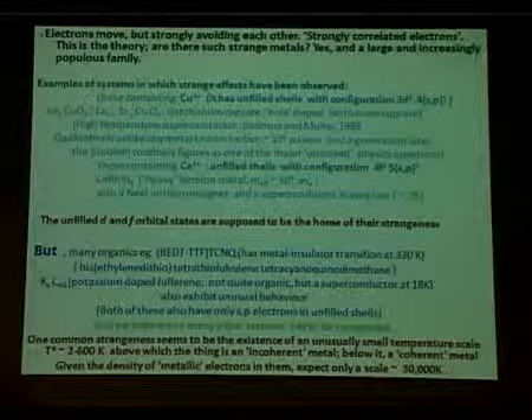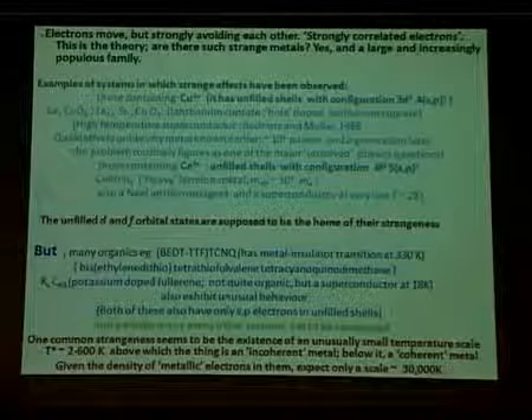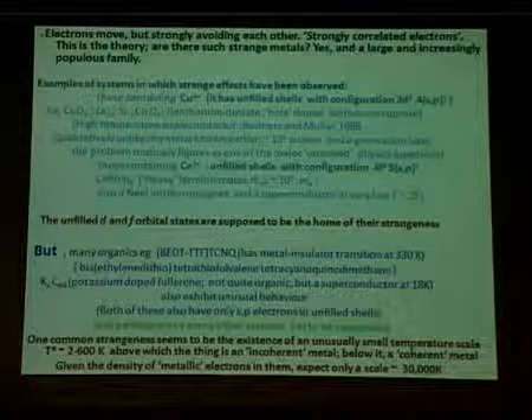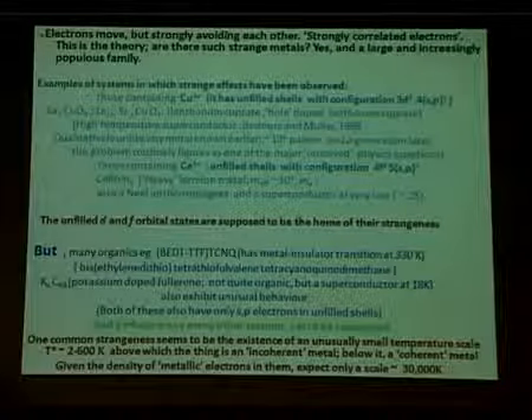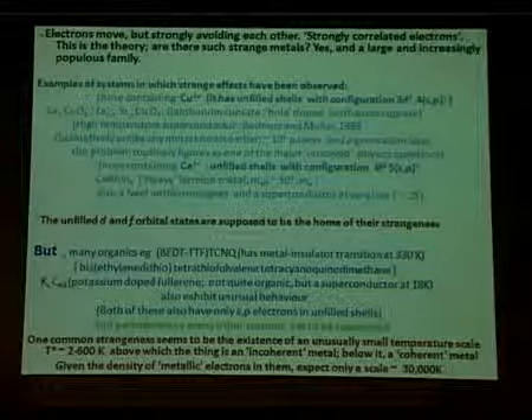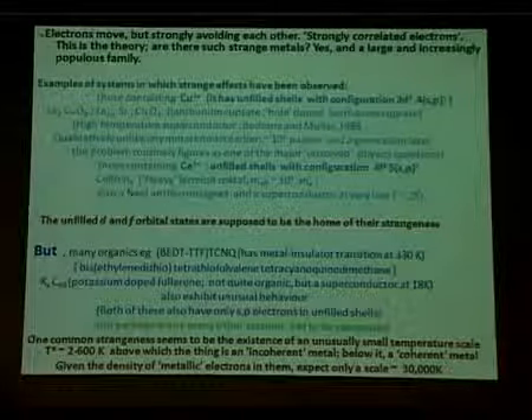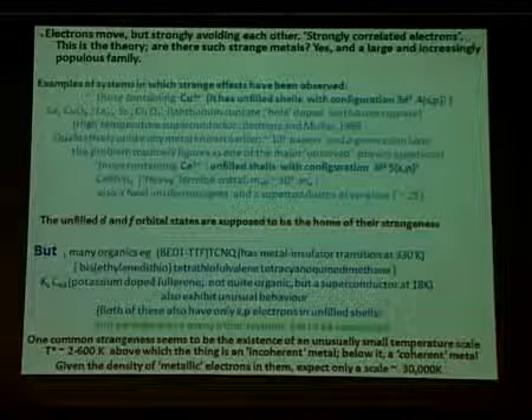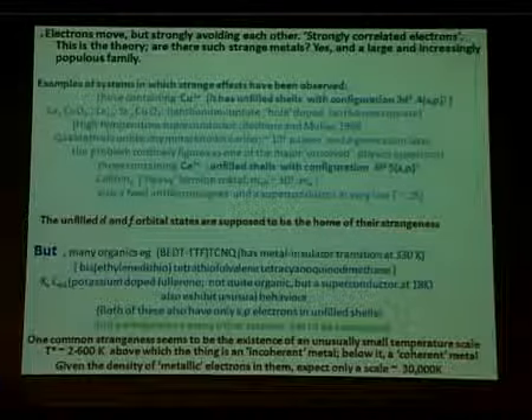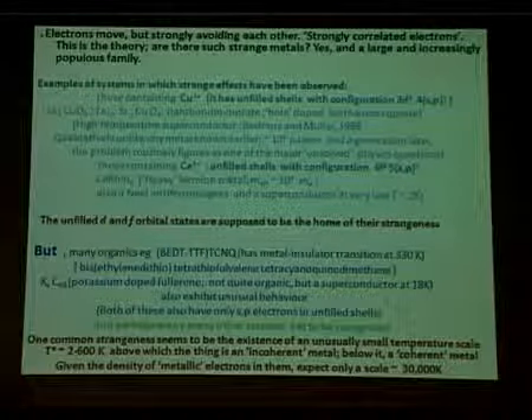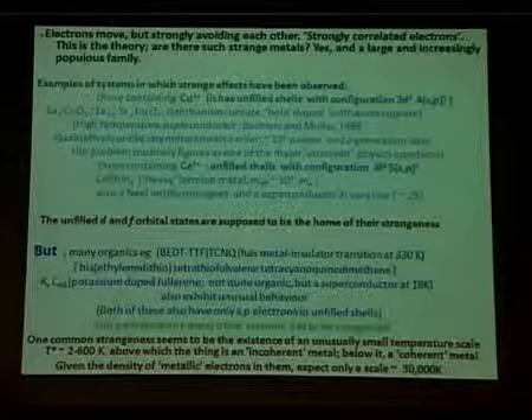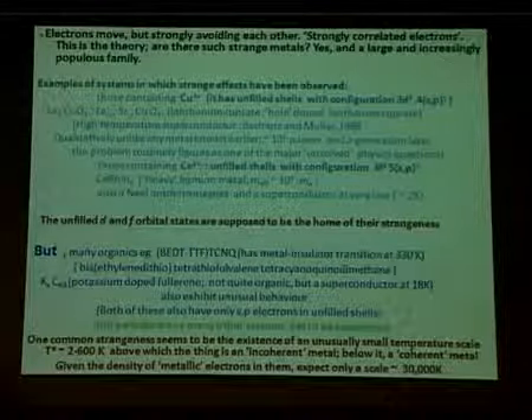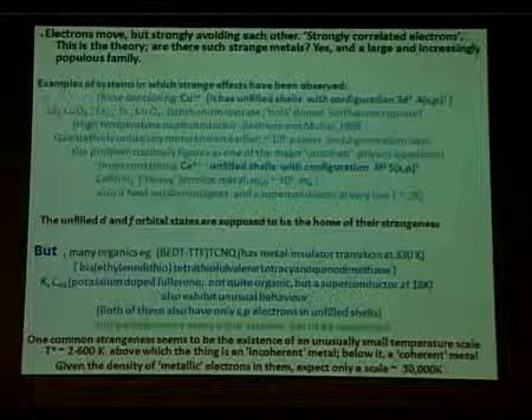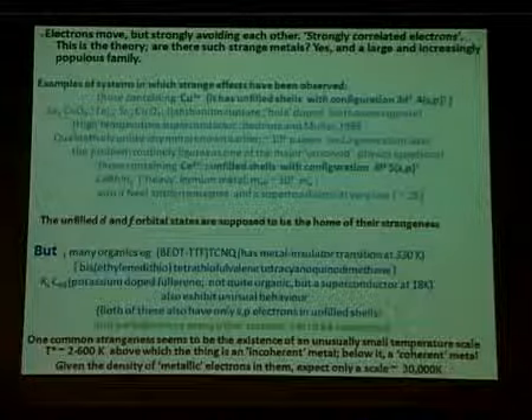Now, the temperature at which something superconducts is called the superconducting transition temperature. That was about 24 degrees Kelvin above absolute zero till about 1986. In 1986, these two gentlemen, Bednorz and Müller, discovered, in a family very closely related to this, superconductivity at temperatures much higher than that, about 40 degrees above absolute zero. Now the world record for superconductivity in cuprates is about 140 degrees above absolute zero.